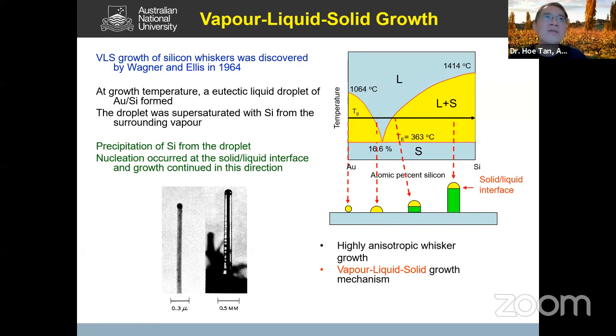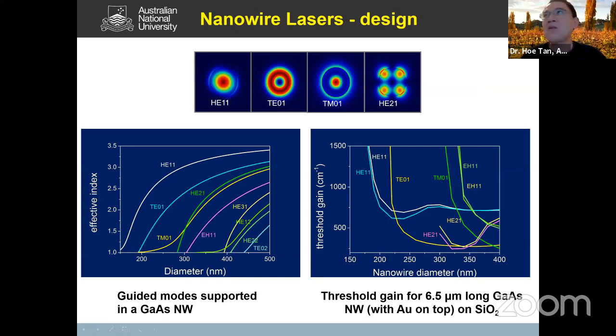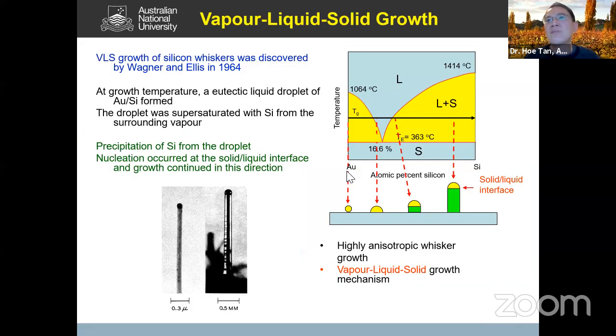This was more than 40 or 50 years ago, but right now we can also do the same thing for other semiconductors like gallium arsenide, the III-V semiconductors. Before I show you an example of our application, we want to grow these gallium arsenide nanowires to make nanowire lasers. But first, in the VLS growth mechanism, the diameter of the nanowire is essentially determined by the diameter of the gold particle that you use.